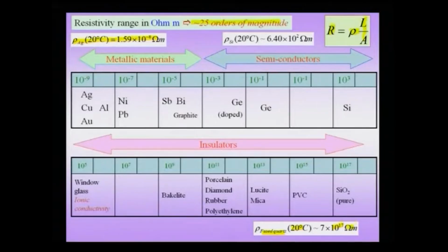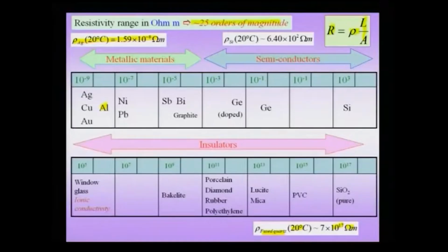So, this is one of those rare quantities which varies by orders of magnitude. Suppose I am using aluminum as a conductor, and on the surface of this aluminum conductor you form an oxide, which is going to be Al2O3. Then you would notice that the resistivity is going to jump by orders of magnitude, and this implies that my electrical conduction is going to be very poor just by this mere process of oxidation at the surface of this aluminum conductor.